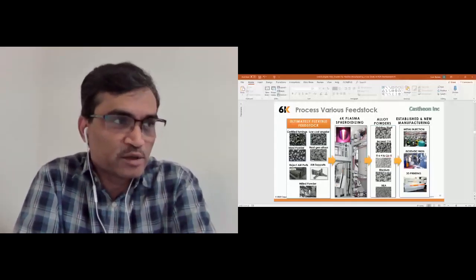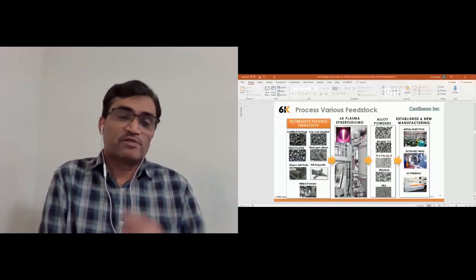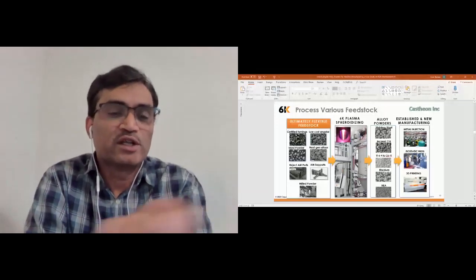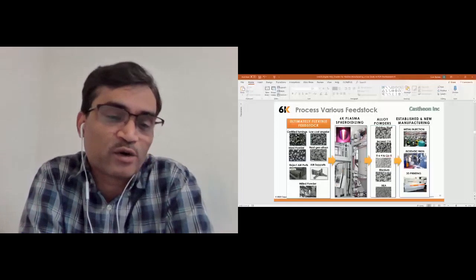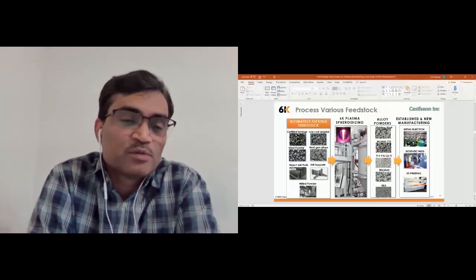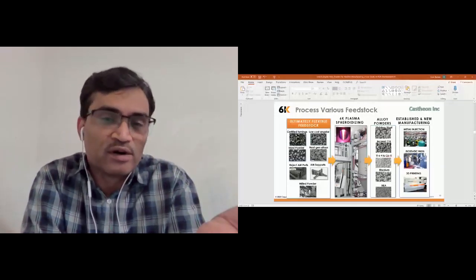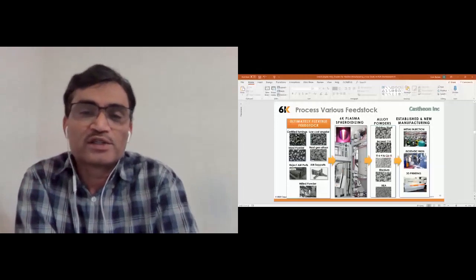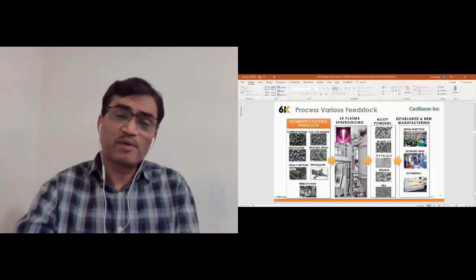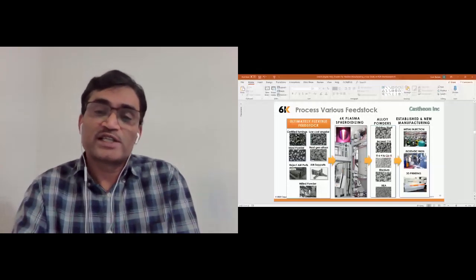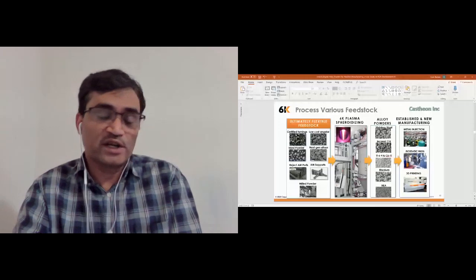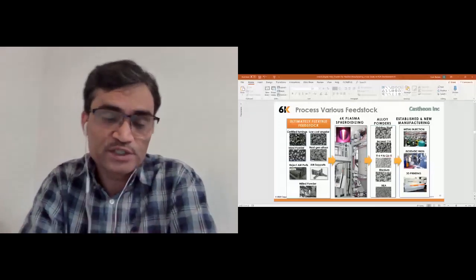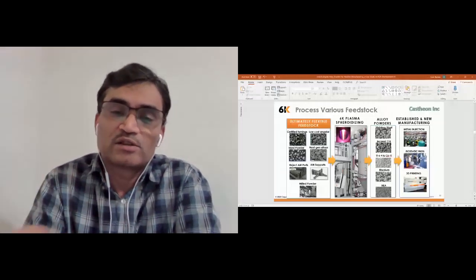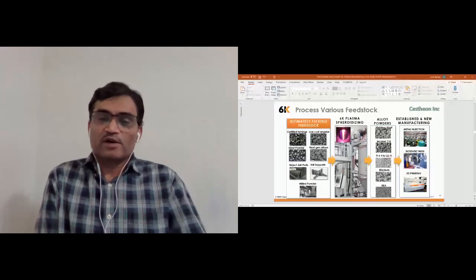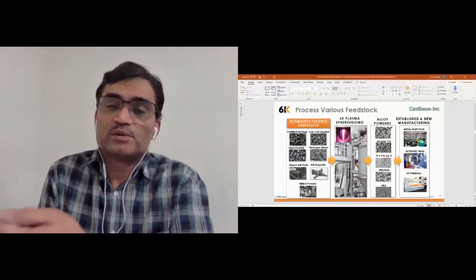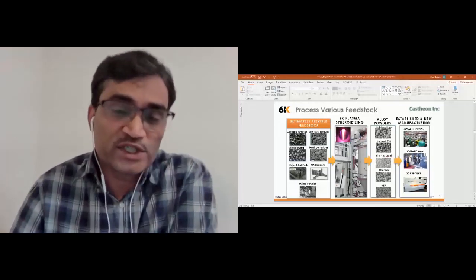We can also use rejected parts. We can turn them down, then mill them and make a feedstock. Our feedstock is basically a milled powder that you can see in the bottom micrograph, with the same morphology. So we can use very rough, irregular powder and convert that into perfectly spherical powders. You can see all these different types of powders that we have produced and demonstrated, from stainless steel and Inconel to high temperature rhenium, and of course high entropy alloys, which is the topic of our discussion today. All these powders can be used not only for additive manufacturing, but are also interesting for metal injection molding and hot isostatic processing.